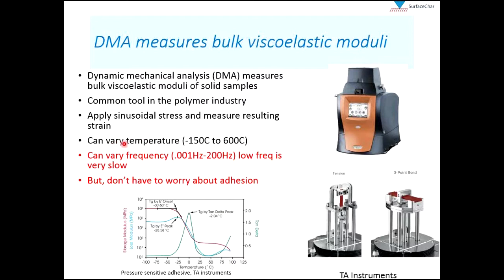It does so as it varies temperature over a wide range, as well as varying frequency. I just want to point out what this frequency range is. So on the low end, I have 0.001 hertz, which is very low, very slow. DMA is not often done at this extreme low frequency because it is a very slow measurement to make. But note also what the upper end of the frequency range is. It's only 200 hertz, which in the realm of AFM measurements, where we're often operating in the kilohertz and sometimes even megahertz regime, 200 hertz is quite low. Also in DMA, you don't have to worry about adhesion, which you'll see will come up obviously in AFM.